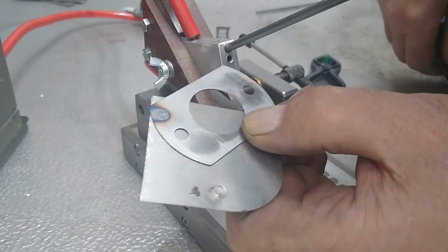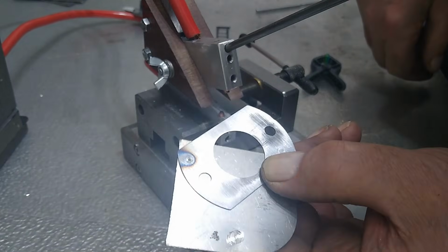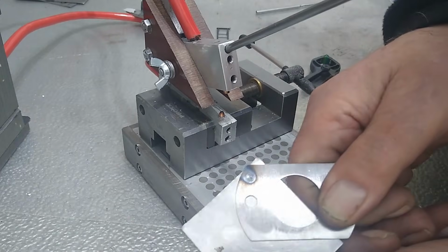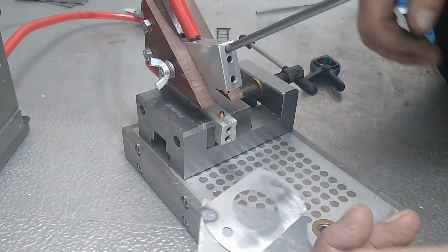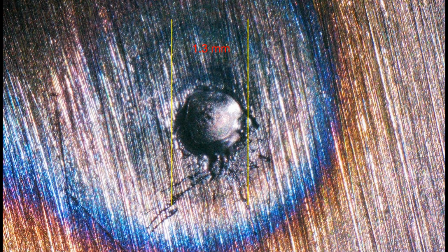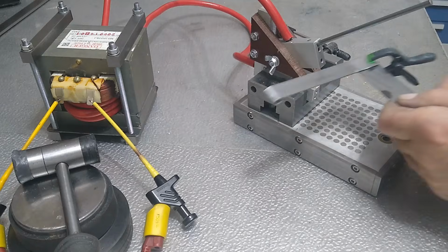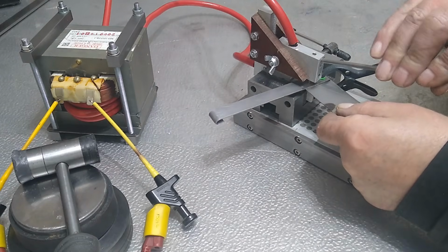And indeed, it holds. There is a weld nugget of about 1.3mm, and I actually have to apply some force to twist the plates apart. However, the weld time is already a full second, which is far longer than I would like. That is probably not a good sign if I want to weld thicker material.